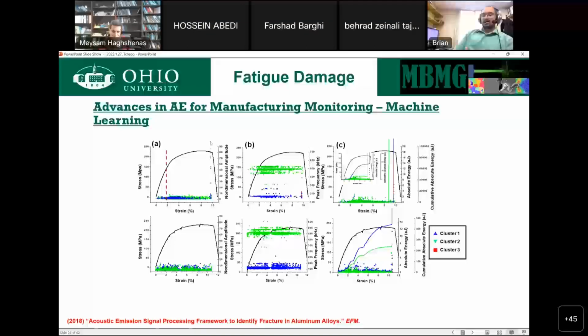And we're able to plot how this evolves over time and connect what we know from in situ observation of the damage with the acoustic emission monitoring to hypothesize what each of these clusters might be representing. The easiest one is the red dots that only happen right at final fracture. That's simple enough. That is the final fracture. What's more challenging is getting into the green and the blue dots. That's because if we look at them, there seems to be a number of different bands within each of these clusters.